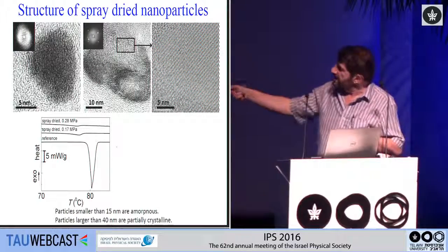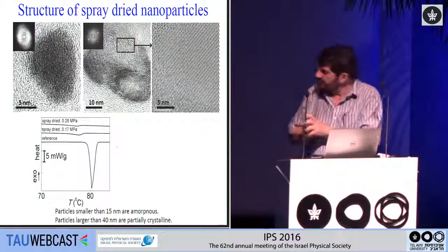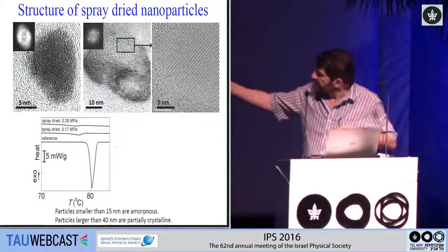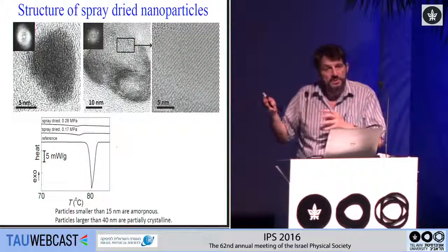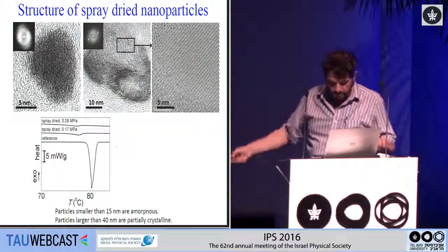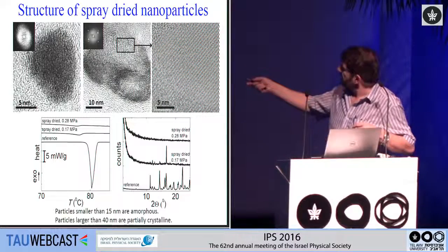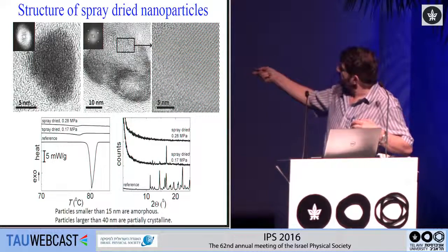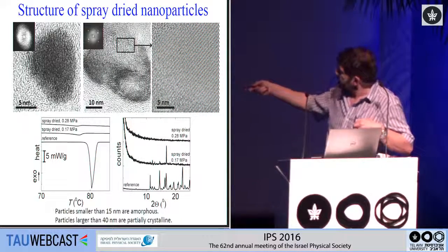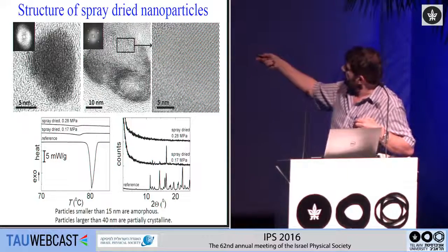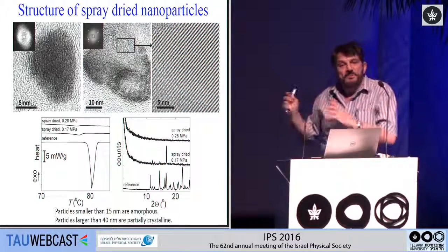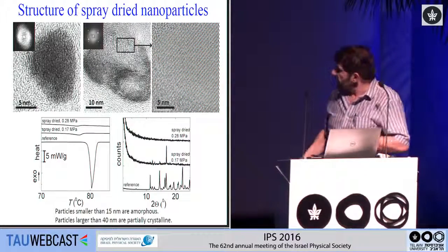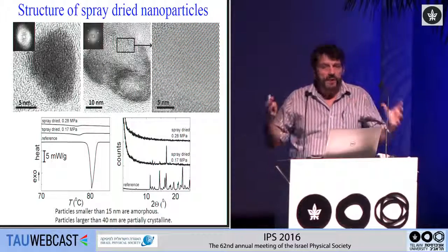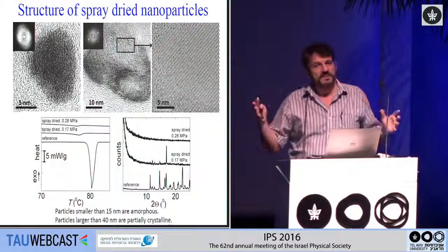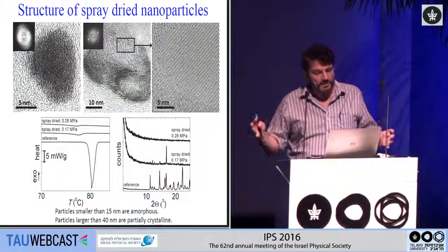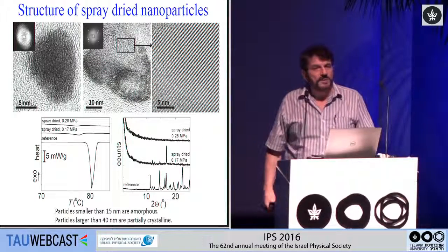You can see this if you do DSC, differential scanning calorimetry. This is a peak. This is a melting peak due to the existence of a crystal. You lose that. If you do scattering, these are the spray-dried particles. This is a reference. This is the spray-dried particles. If you make them small enough, you completely lose crystallinity. So basically, if they're about 20 nanometers, 15 nanometers or smaller, they're completely non-crystalline. They're amorphous. So how do we understand that?